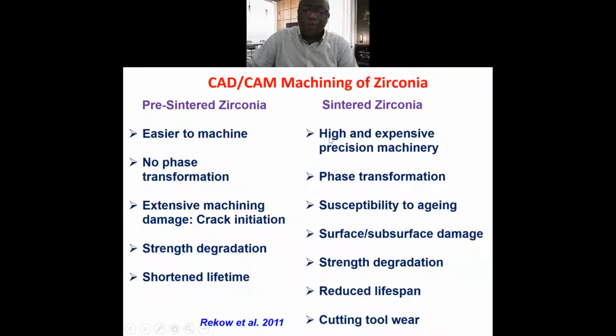But there is a possibility that the phase can transform from tetragonal to monoclinic. Then it is also susceptible to aging, in which case, when there is a phase transformation in a humid environment, the fluid will exacerbate the transformation and also will lead to pulling out of the grains. That is known as aging.